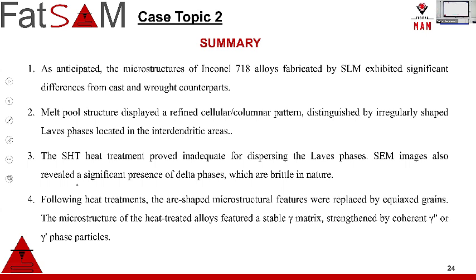That's the issue. If you are doing additive manufacturing, you should think, I keep saying that, it's a welding methodology. That's why new methodologies are coming, which is my favorite, cold spray. It's coming because it's just a kinetic metallization, low heat. It's a very effective way, and it will be very popular in the future. For big parts, DED still is the most attractive one, but for rapid prototyping and small parts, SLM is the best. But in certain materials like titanium alloys or stainless steels, EBM can be the method of choice.